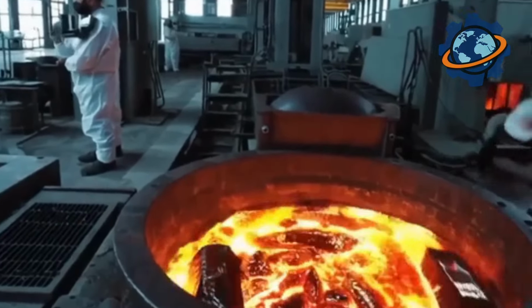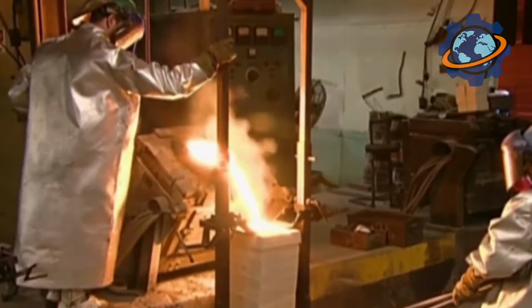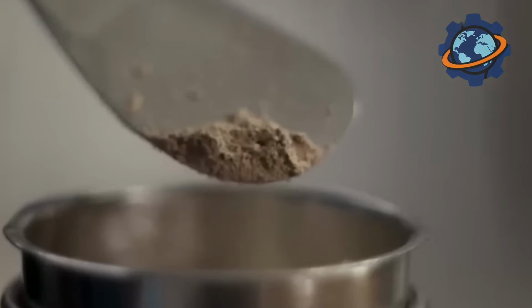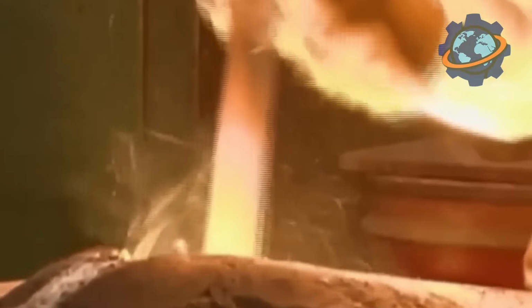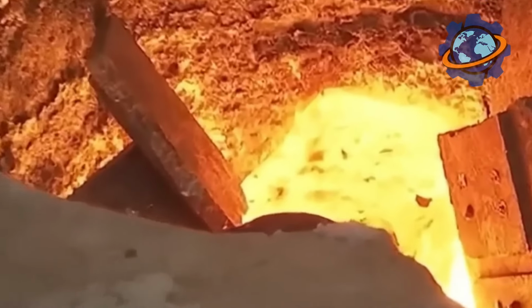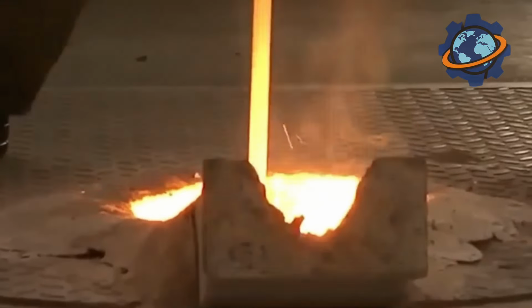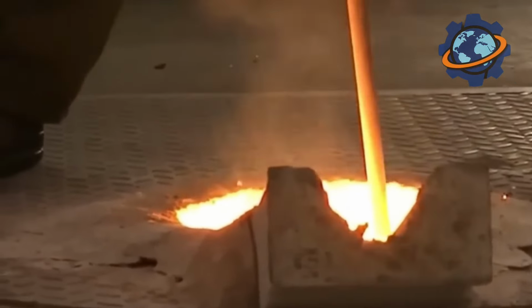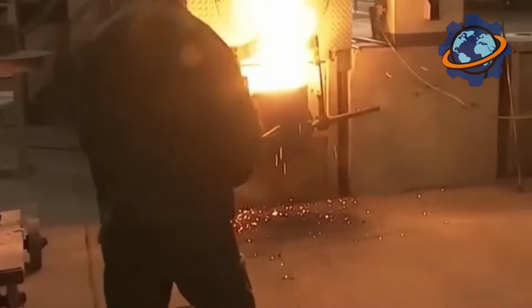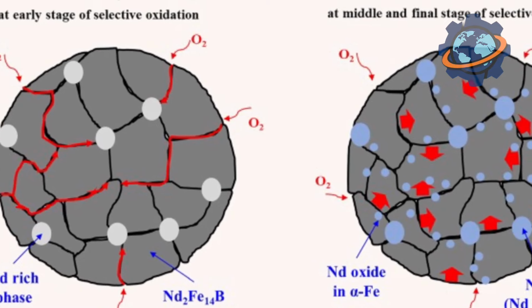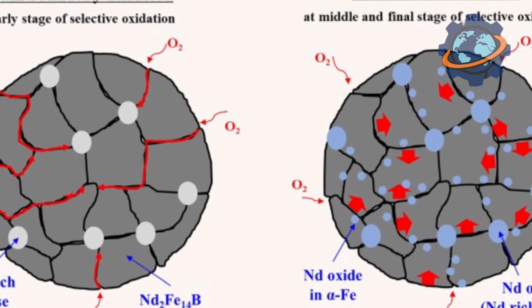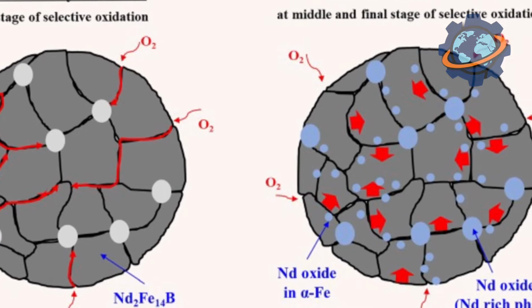The exact composition of the alloy is a trade secret for many manufacturers and varies depending on the desired final characteristics of the magnet. The weighed components are placed in a specialized vacuum induction furnace. The use of a vacuum is critically important as it prevents the oxidation of the rare earth metals and other components at high temperatures. Oxidation would lead to the formation of undesirable phases, which would degrade the magnetic properties of the material.